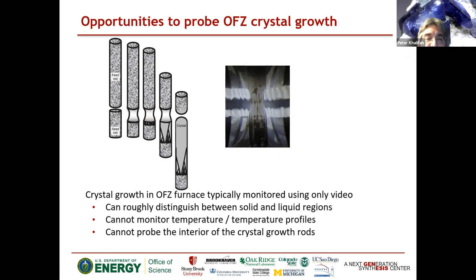You balance this by feeding in more material from the top through the feed rod to keep the zone stable — not easy to do, but that's how the process works. Since you're growing on top of a powder rod, you have lots of homogeneous nucleation, so you start with many small crystals. As the growth proceeds, the grains that grow fastest win out. What you want to end up with is a single crystal at the end of your rod that's centimeters long and useful for the types of applications described.